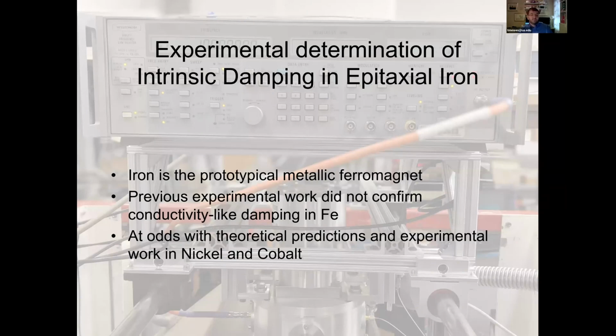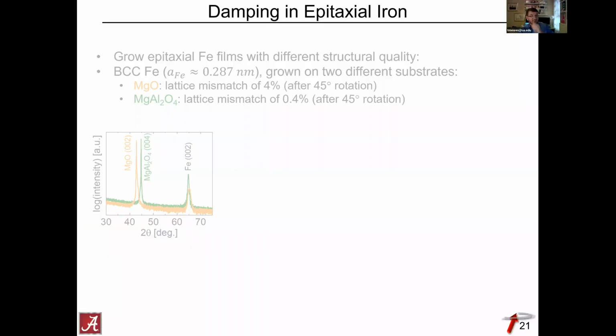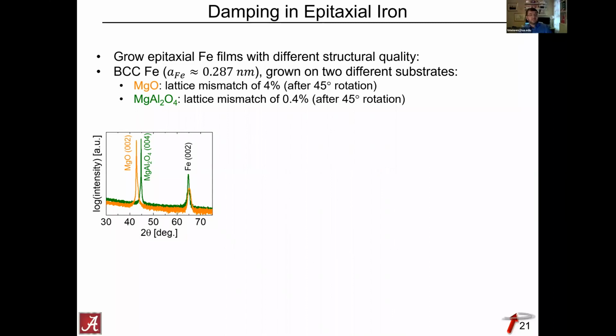So in collaboration with Satoru Emori, we tried to find out what's going on in iron, whereas for nickel and cobalt, this contribution had been confirmed a long time ago. Let's take a look at the system that we investigated. These were epitaxial iron films grown on both MgO, which has a lattice mismatch of about 4%, and magnesium aluminum oxide, which has a much lower lattice mismatch of about 0.4%.